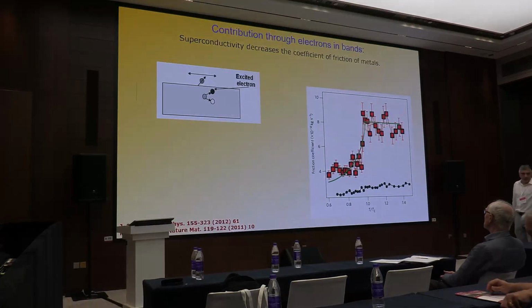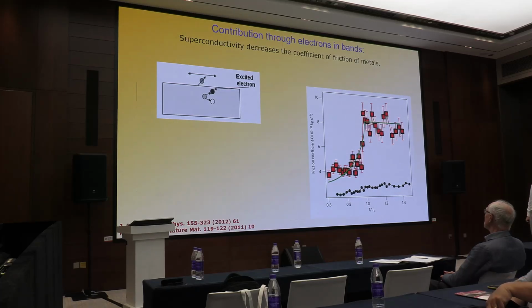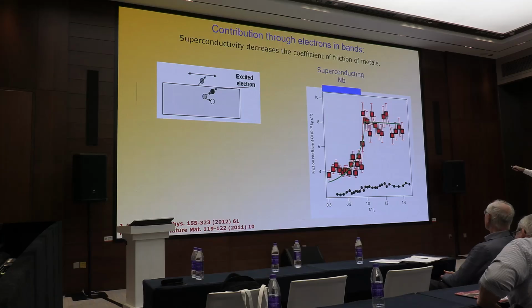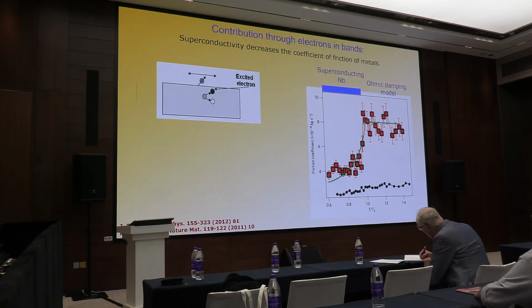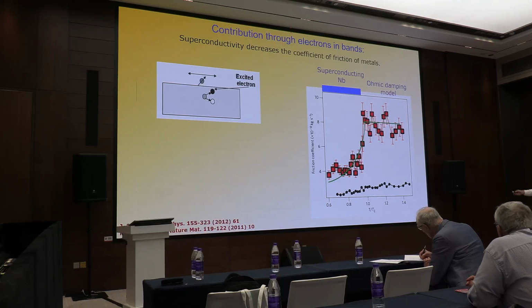Okay, but I will go back to this in the next slide. Now I would like to introduce another contribution, because we have, for example, contributions in electron bands. For example, superconductivity decreases the coefficient of friction of metals. Here is niobium in the superconducting state, and you can see that the friction coefficient decreases in the superconducting state, and this is niobium after the superconductivity transition. Here is normal niobium, and this is superconducting niobium.